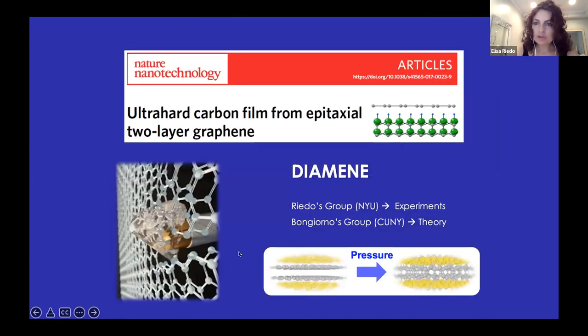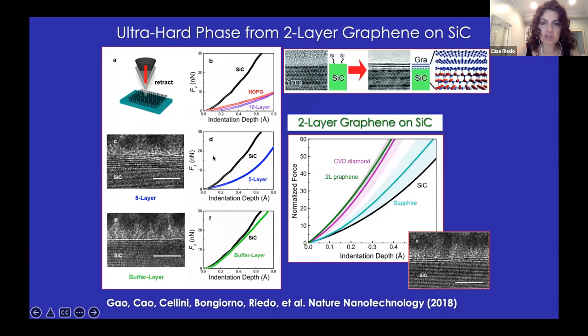By doing this type of study, we have recently discovered something very interesting, which is a phase transition of epitaxial graphene, which is graphene grown on silicon carbide, when under pressure, into a diamond phase. The transition occurs at room temperature, and under the action of the AFM tip, we were able to detect a change, as you can see here.